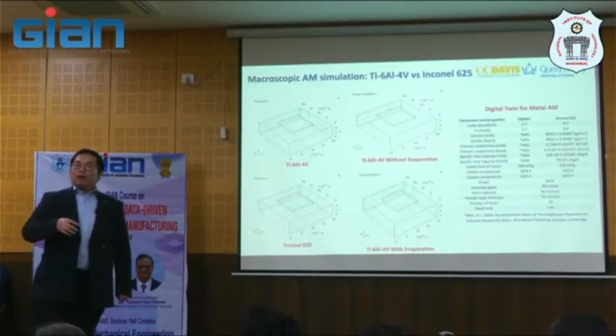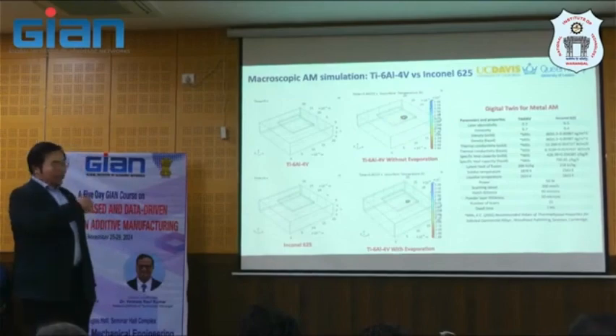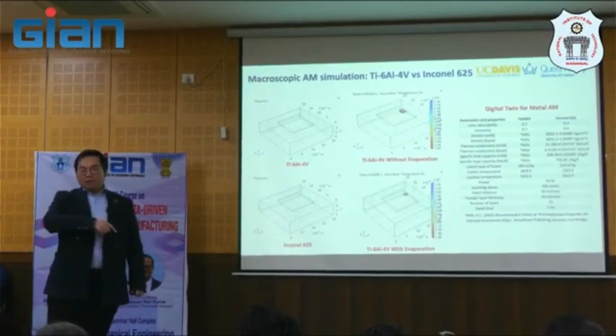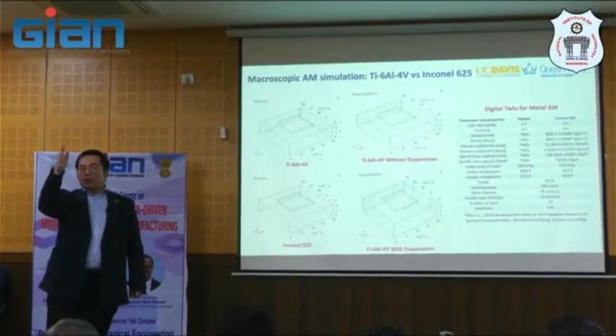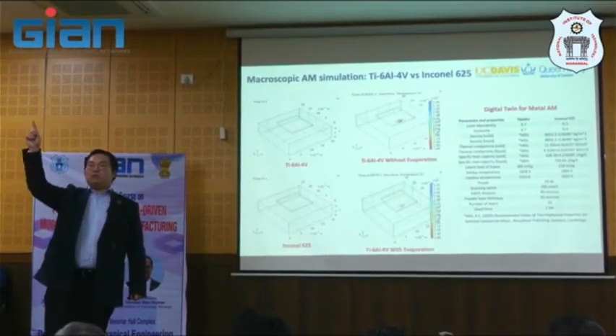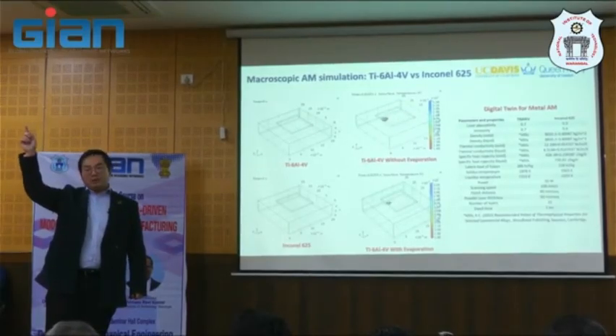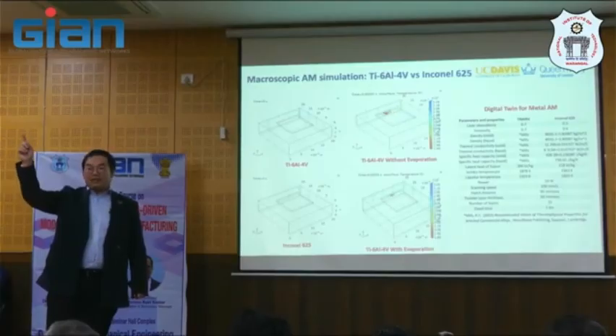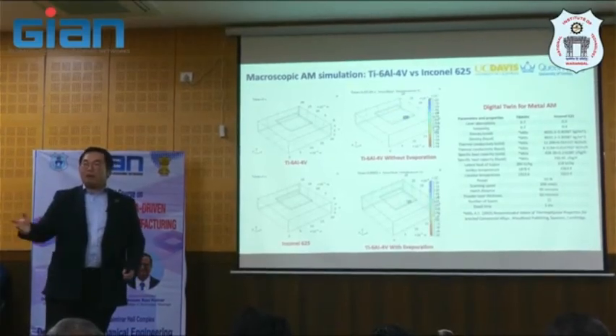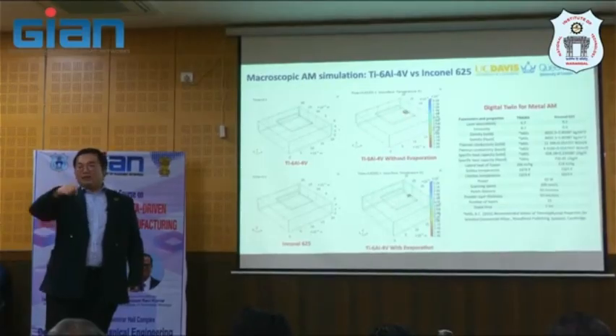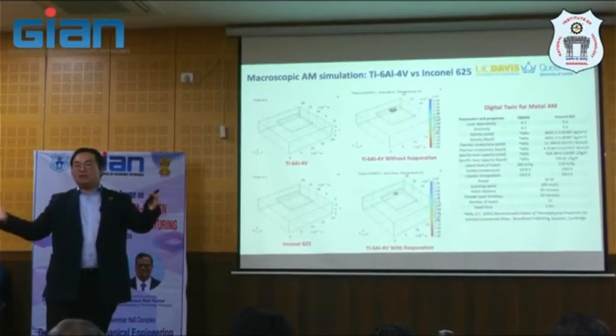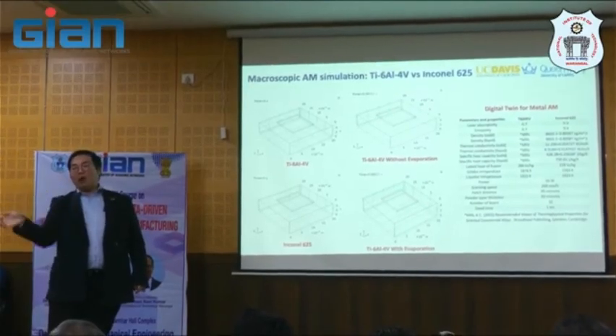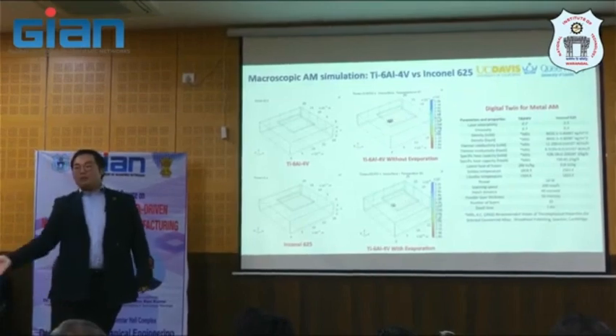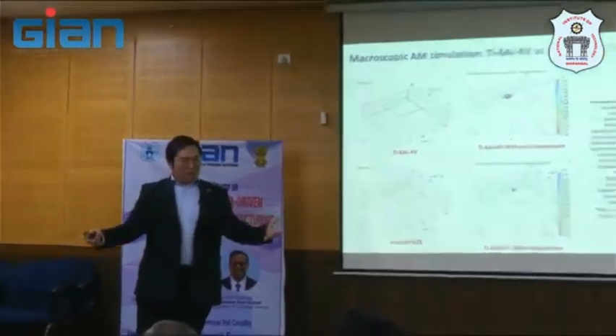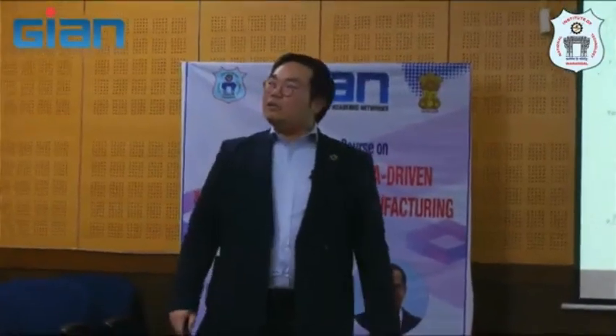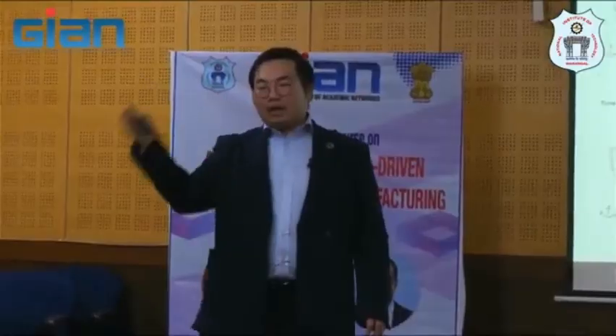Yeah. When evaporation kicks in, because if you have the normal thermal diffusion equation, when you solve it, it can go to a ridiculous number like 10,000 degrees centigrade, and this is not realistic, because nature does not allow this to happen. Once you get to the boiling temperature, there will be some dissipation. So the temperature usually never goes up beyond the boiling temperature. So we damp that temperature down due to the latent heat.